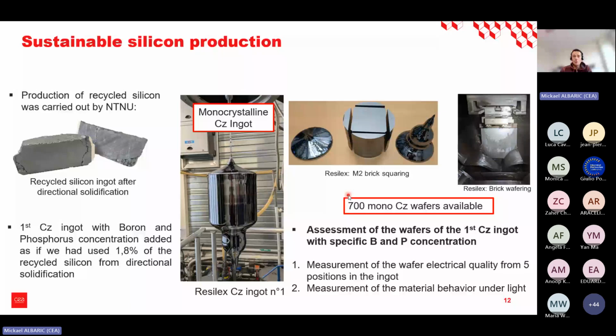And these wafers have been used in the frame of the Resilex project for an assessment of the wafer from the first CZ ingot with specific phosphorus and boron concentration. We did two kinds of assessment. First, some measurement of the wafer electrical quality has been performed at 5 different positions along the ingot, and we also measured the behavior of this material under light and under illumination. So this is what I'm going to present in the next slide.